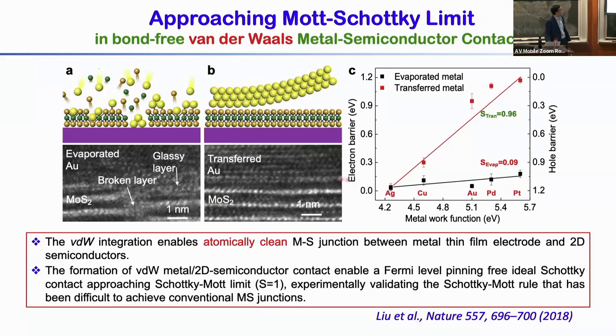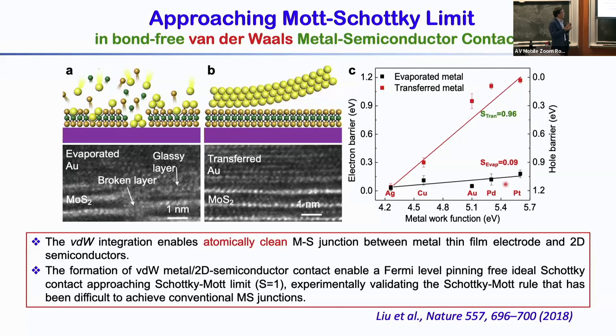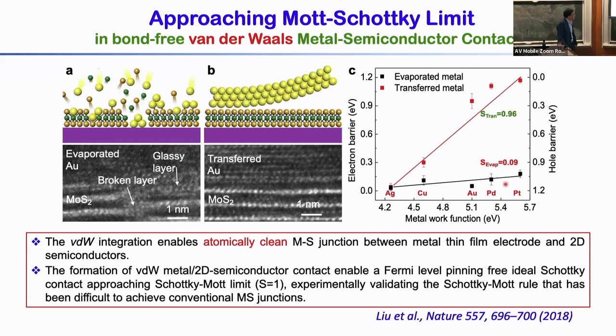We can do this with a number of different metals and try to determine the barrier height versus work function relationship. In comparison, we find that the barrier height actually scales very well with the metal work function with a slope of nearly one. In contrast, if we use deposition to make the same contact, the slope is around 0.1. This really highlights that with this van der Waals integration approach, we can actually maintain a Fermi-level-pinning-free interface and achieve this Schottky-limited, ideal contact behavior.